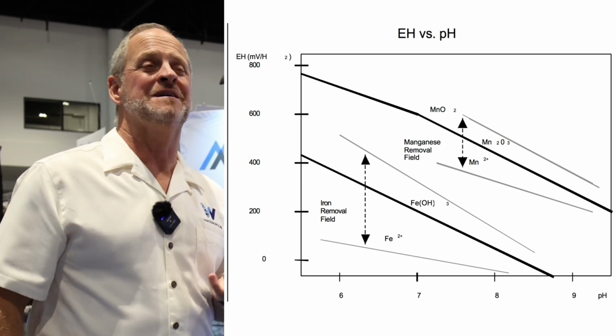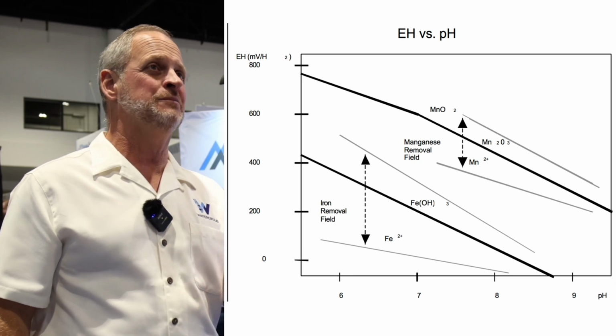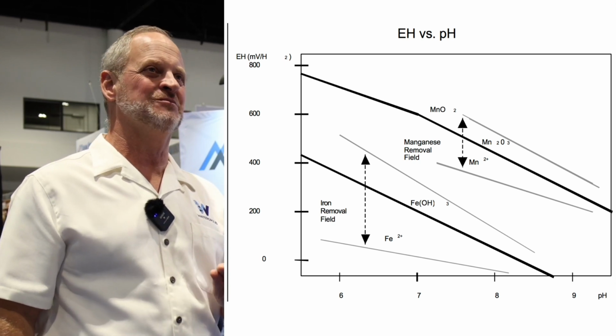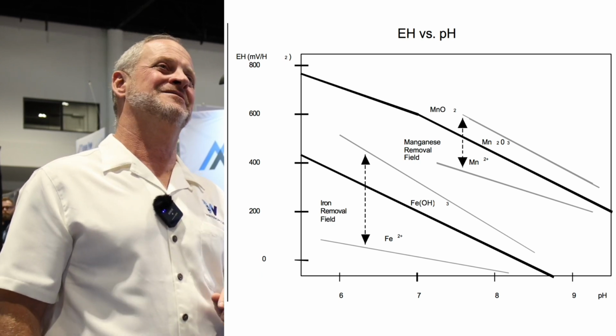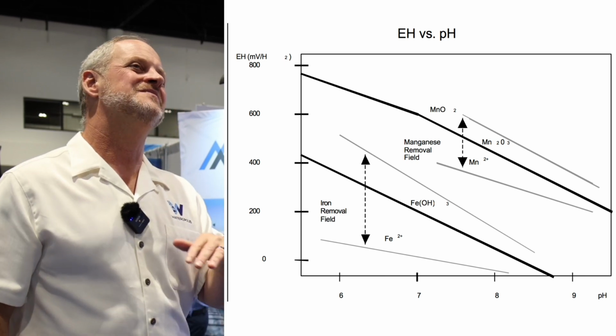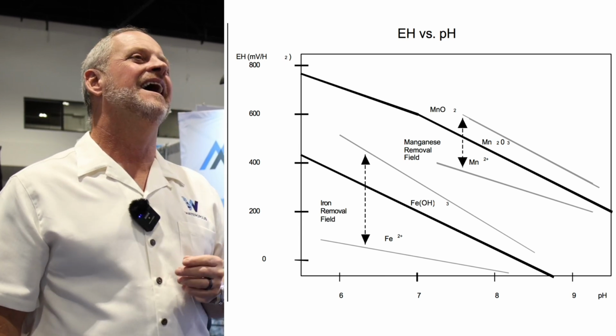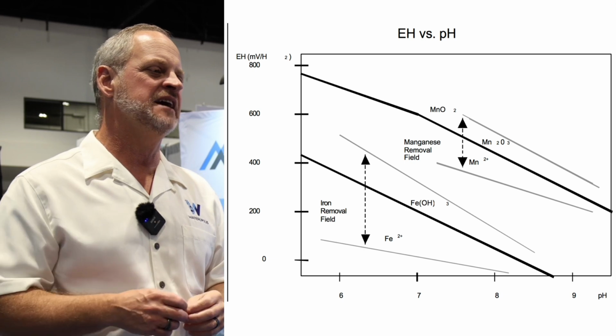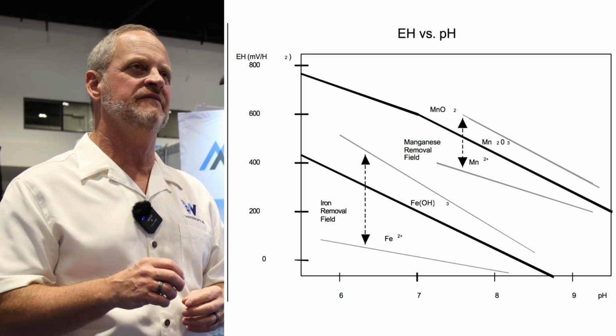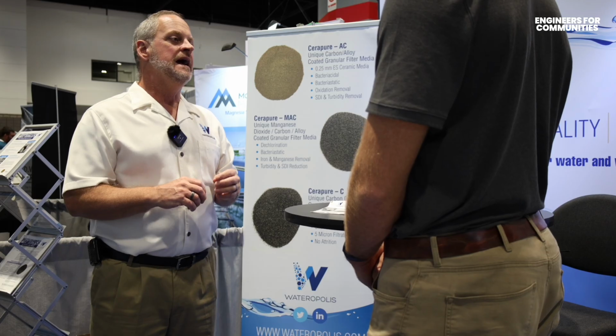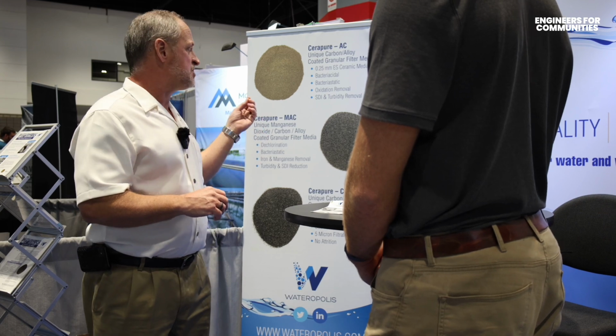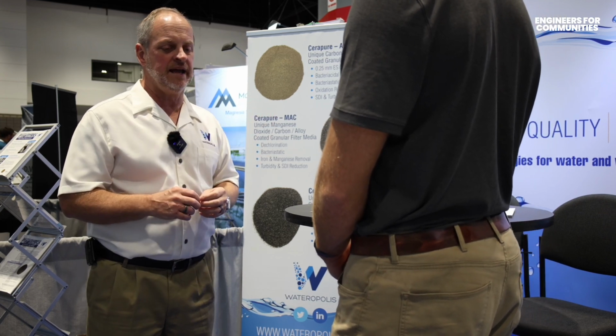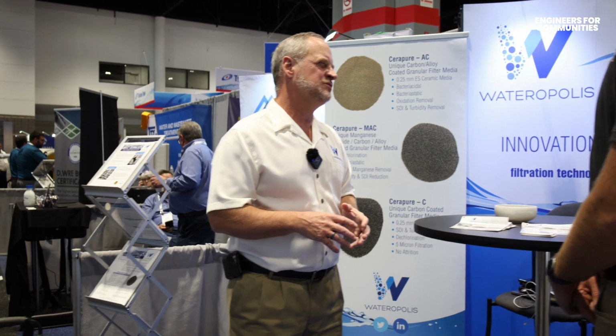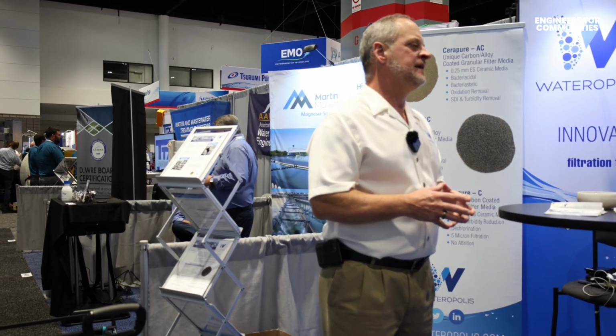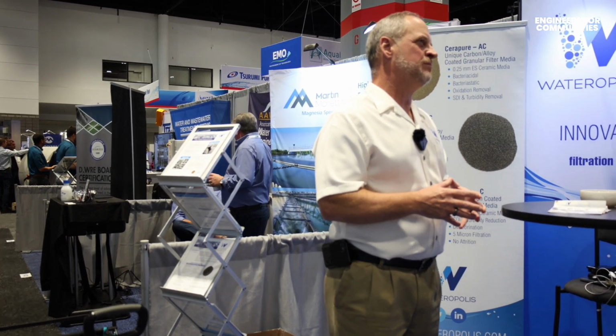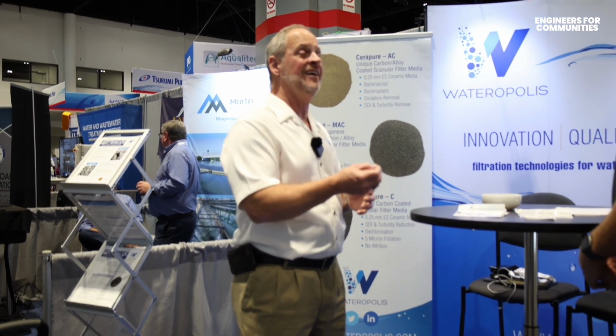A lot of people don't like permanganate because if you do it wrong, you end up with pink water, and nothing gets a consumer hotter than pink water coming out of their tap. So that's so interesting, because that's exactly what I'm seeing right now. Yeah, pink water is a side effect of using permanganate and not having that dosage nailed down. If you use a manganese coated material, which we make, you can mitigate some of the potential for that pink water, but a lot of people don't want to use permanganate, and it helps catalyze that crystal structure.